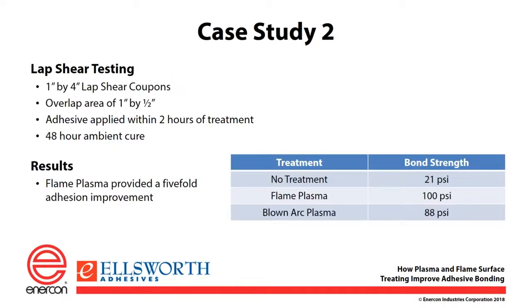Same test method, 1-inch by 4-inch coupons, 1-inch by 1/2-inch overlap area. In this case, the adhesive was applied within 2 hours of the treatment, and the adhesive was allowed to cure for 48 hours before testing. Without any treatment, we only had a bond strength of 21 psi. With flame plasma, this was increased to 100 psi, so almost a 5-fold increase, and blown arc plasma increased it to 88 psi.